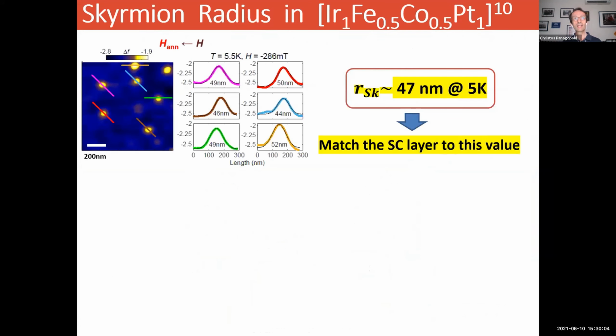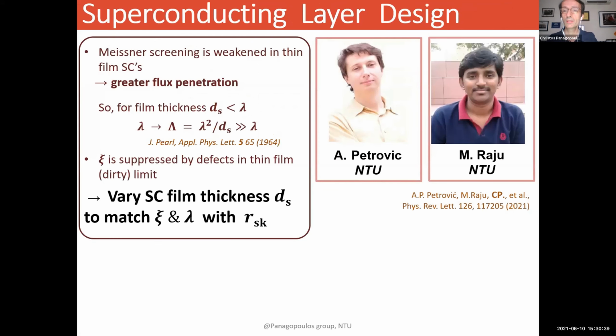So having selected the right heterostructure for our study, we are able now to identify the skyrmions in more detail and measure those and find that the specific material that we are interested in would have the right size of skyrmions. And in particular, for this material shown here, we have a radius which is approximately 47 nanometers at 5 degrees Kelvin and below. So the next thing is to match the superconducting layer to this value. And this is work that actually was done between my two researchers, Alex Petrovich and Raju. So they worked very hard together in order to get the right parameters and build the right samples so that